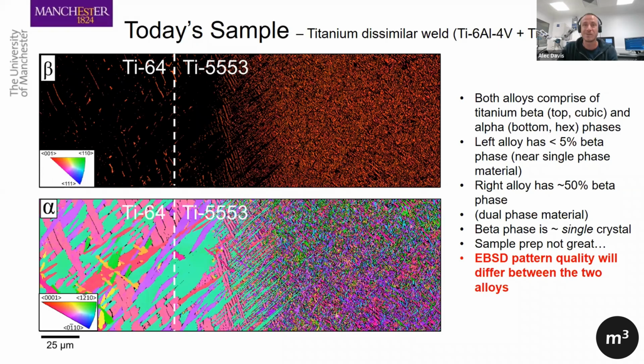And the last thing I want to mention about this sample is that I polished this not very well, and I did it 6 months ago. We wanted to use this sample because we didn't want people thinking that we were using, you know, a perfect silicon sample, which is why we'd be getting good patterns and really strong signals. We wanted to use something a bit more realistic for everyday experiments, just to show that all of these things are possible, even if the sample isn't the best.